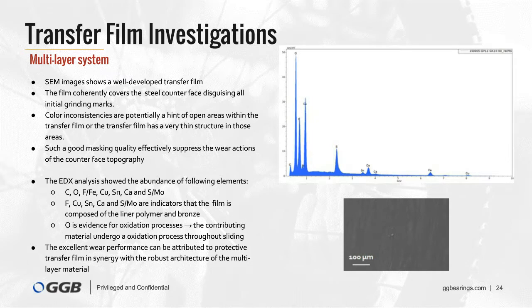We also investigated the chemistry behind the transfer film. What we see here is that we have an abundance of the following elements: CO, Fe, F, Cu, Sn, and many more. This is an indicator that the low peak of Fe shows the transfer film is really covering the whole surface. We also see the other elements, which come from the PTFE, bearing liner, and the bronze structure. So the transfer film is composed of the bearing liner plus bronze.